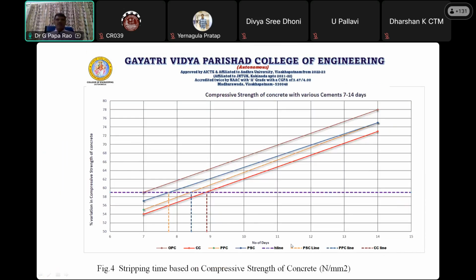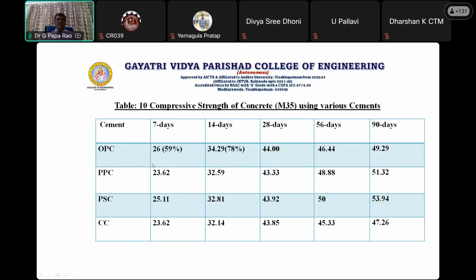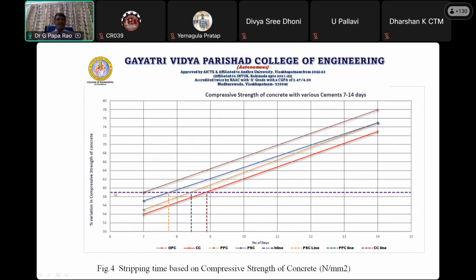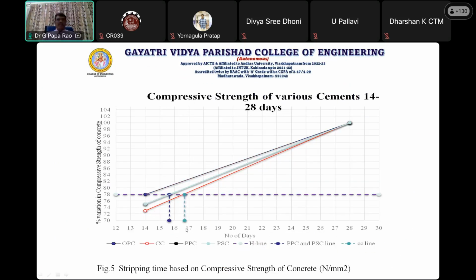Here again we have plotted the graph between the percentage compressive strength of concrete for various types of concrete with various types of cements. Here our OPC got 59% at 7 days. So we have taken this 59% as the baseline, and we have observed at what duration the 59% of strength is reached by other cements like PPC, PSC, and CC. If you see, our composite cement reaches it at nearly 9 days instead of 7. Again, PPC takes 8 days. And again at 14 days also.